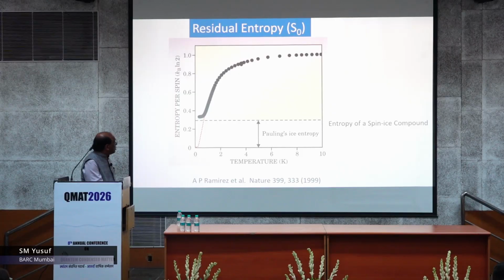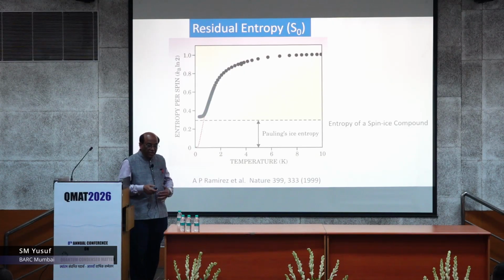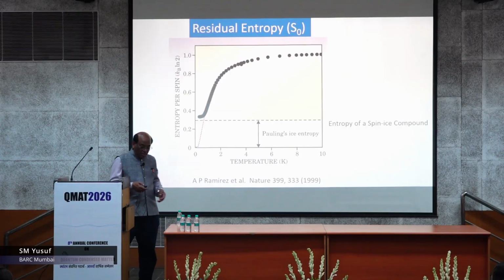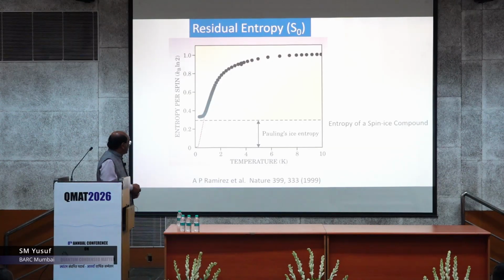As far as the residual entropy is concerned, this is the entropy per spin. As you know, if you cool the specimen and come to almost zero temperature, you see that still some entropy is left in the system. It has not been released. So this is called the residual entropy, and if this is high, that means that much entropy is available in the system, and that is due to this zero temperature quantum fluctuation. And this view graph was, of course, taken from this famous paper.